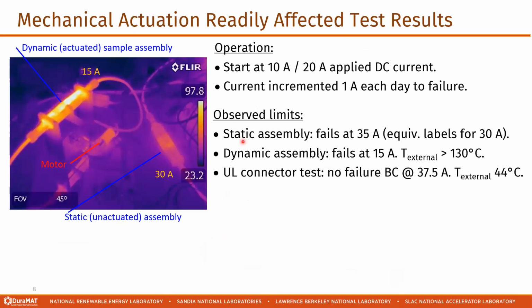So here's the image that summarizes the results of the benchtop experiment. Let me explain. We started at a 10 amp initial current for the actuated or dynamic assembly, and then we actually doubled that current for the static component. So we're comparing them side by side, right? Each day we incremented the current up by 1 amp until we got to the point of failure. The immediate observation, here and in separate examinations where we looked at one component at a time, is that the static assembly was failing at about 35 amps. The components are equivalently labeled for a 30 amp, so this is doing at least what they say it should be doing. The dynamic assembly is getting much hotter in this image, even though we're running half of the current, and this is failing at about 15 amps, reaching temperatures of 130°C.